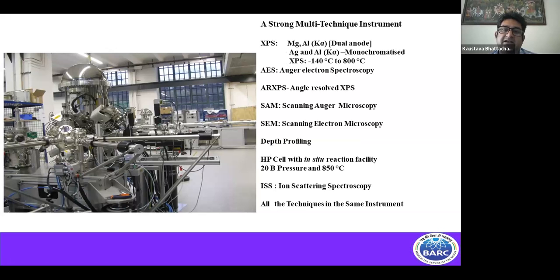We use ions in the energy range of 0 to 5 keV. As we understand, in XPS we are measuring the kinetic energy of the electron. If we change the polarity of this detector, we can measure the kinetic energy of the ions also.